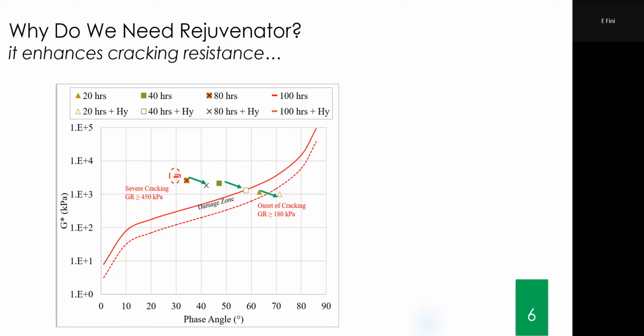Obviously, if you have another measure, let's say now I'm showing you G star, or the stiffness, or strength, or crack resistance, any other indicator that you measure, if you know the results before aging or at a lower level of aging, you want your rejuvenator to give you back the good stuff you had. So conceptually, the meaning of rejuvenator is revitalizing the properties that are lost, revitalizing the characteristics that you no longer have.